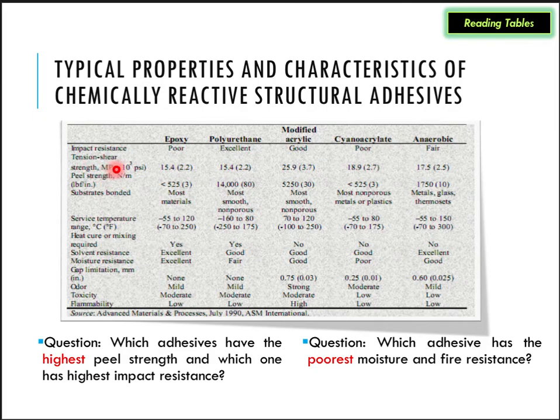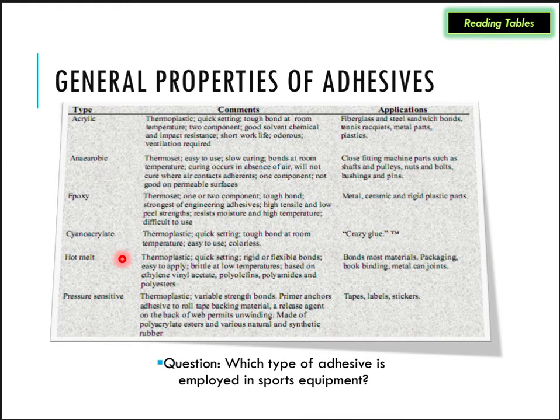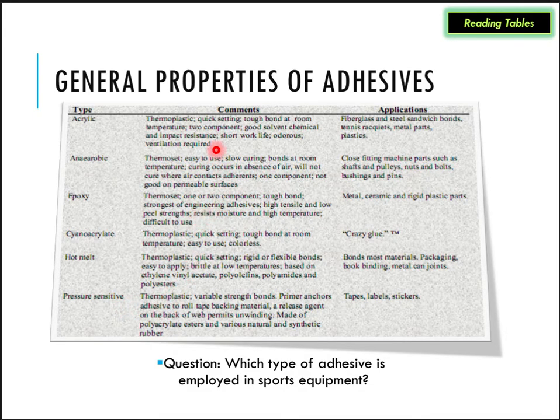For tensile shear strength, modified acrylic gives 25.9 MPa, which is the highest. However, when we consider both solvent resistance and moisture resistance, epoxy has the best performance. Based on the properties and compatibility of the adhesive, we can choose different types based on our application. Different applications have been tabulated with comments on which type of thermoplastic or material has been used. Students can go through this table and answer the questions below each table.